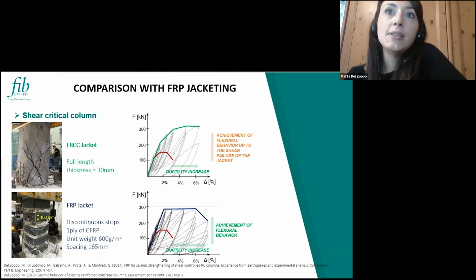And this is the comparison between the two specimens strengthened with the two different strengthening techniques, of course, always in comparison with the bare behavior, that is the red one. So we can see that both systems are able to increase the flexural capacity of the specimen, avoiding the shear behavior and allowing the achievement of the flexural capacity of the member. So in both of them, we are achieving the flexural yielding.